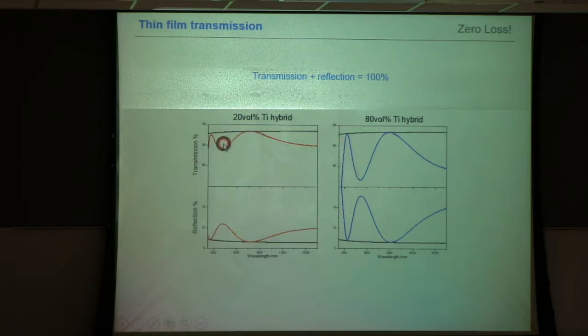And wherever you have a minima in your oscillations, you see that's where the reflection is highest. They are really mirror images, again confirming that wherever we don't have transmission, we have reflection, as expected. So the material is pretty good. Why is that? It took us actually ages.